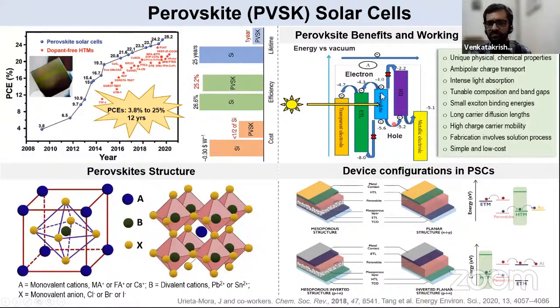Okay, because of the ambipolar nature of the perovskite, you will be able to use the perovskite in any of these device configurations. That shouldn't be a problem. Either the NIP device or the PIN device. Mesoporous structure devices were used earlier. Now the planar configuration is what is commonly preferred. And what you have is the swapping of these layers in these two device configurations. Okay, what you see here is the hole transporting layer next to the metal contact, but in the other case, you have the electron transporting layer adjacent to the metal contact.